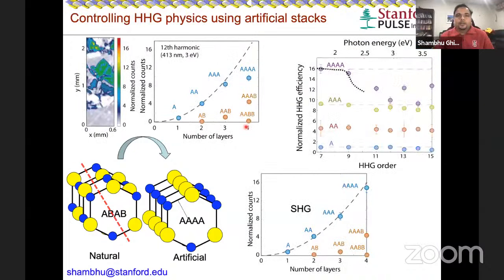And in the other configurations, such as AB and AAB configurations, for example in AB, you reduce the signal of even orders, just because the system recovers inversion symmetry. And so on. This is the entire spectrum as a function of the number of layers, and you can see a fairly nice quadratic increase in the harmonic intensity, but some deviations. For example, for the 12th harmonic, this harmonic is above the band gap, and we can see where the absorption starts to kick in. As a comparison, we also measured the second harmonic, and that's of course nicely quadratic for the AA configurations.